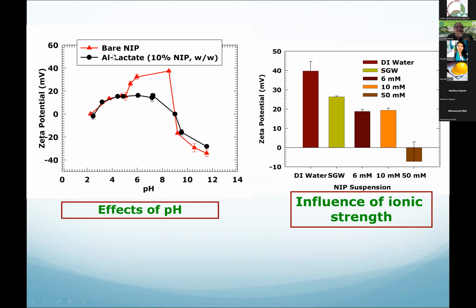And then we looked at the effect of pH. You saw that one in the previous case, aluminum lactate. We used 10% of NIP, and then we looked at the effect of pH. So we control the pH, change the pH to 12, and looked at the zeta potential. As you see, the pH effect is significant. As the pH increases, the charge increases, and then after a certain pH, the surface charge decreases. So the pH also has an effect in addition to the concentration.